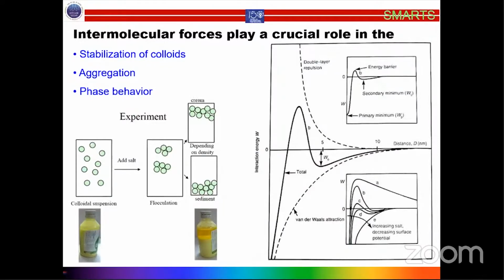You know that the intermolecular forces acting between the colloidal particles decide the stability of the system. They decide the aggregation phenomena and phase behavior, and this is what can happen. It can cream or it can sediment depending upon the density mismatch. So what is needed here is a very strong repulsive interaction between the particles. If the interaction is very strong, the net force, that is the sum of the repulsive interactions, essentially comes from the charges at the interface of the particle or the kind of stabilizing moieties, sometimes a polymer, where the interaction forces are steric.